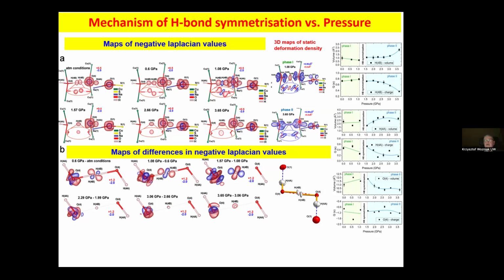This is deformation map, clearly showing flow of electron density through this bond. But even more interesting are maps of differences in negative Laplacian values. So from Laplacian distribution at 0.6 gigapascals, we have taken away Laplacian distribution at, say, ambient pressure. So we can see that at first, concentration of charge at this maxima is taking place, and depletion of charge in this blue area. When we go from 0.6 to 1.08 gigapascals, this process is strengthening. We have clear depletion of electron density from the center and bigger maxima.